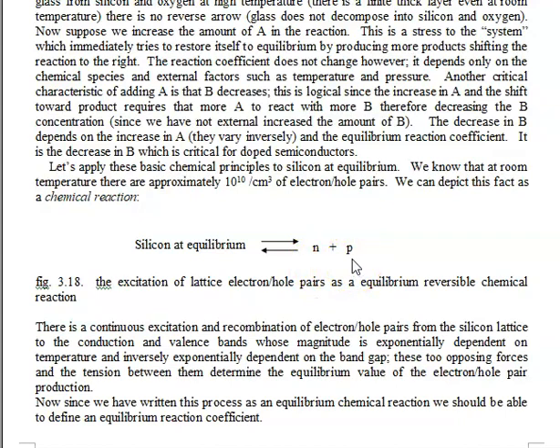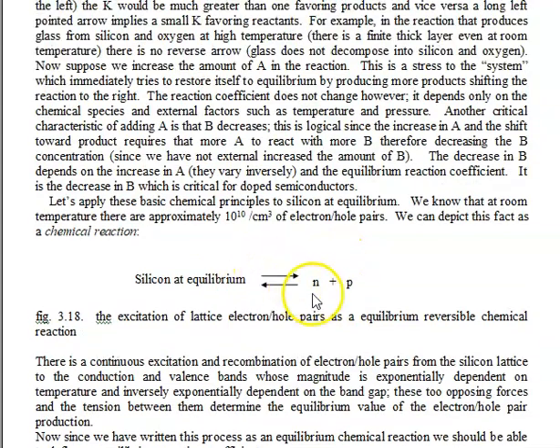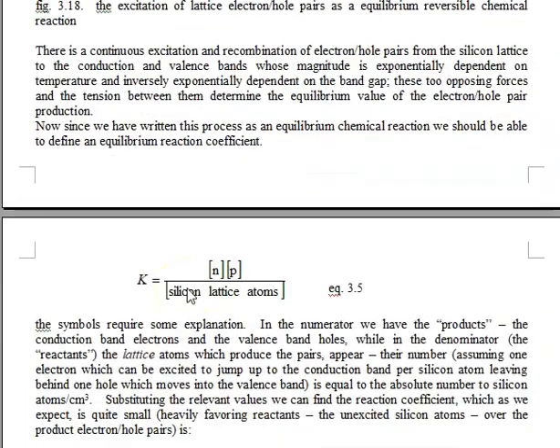Nothing to do with doping yet. We're going to get to doping in just a little bit. But right now, this is only thermal excitation. But it's the same thing. Product of reactants divided by the molar concentration of silicon. So it's an equilibrium reaction coefficient, product N times P divided by the concentration of silicon lattice atoms. This is something we actually calculated in the last session, which is precisely why we did that. And you may recall that it is 10 to the 22. What is N? 10 to the 10th. What is P? 10 to the 10th. They always must be equal if there's no doping.